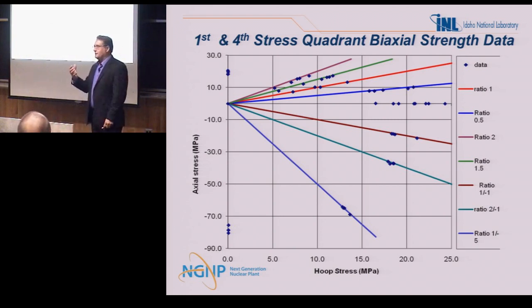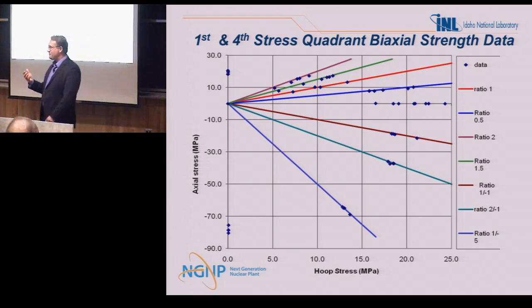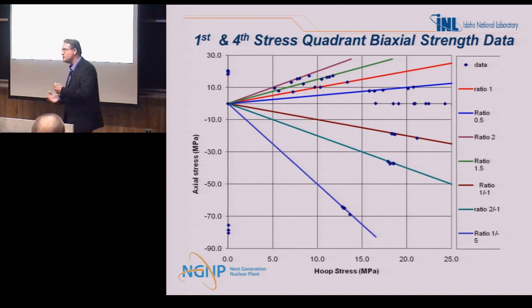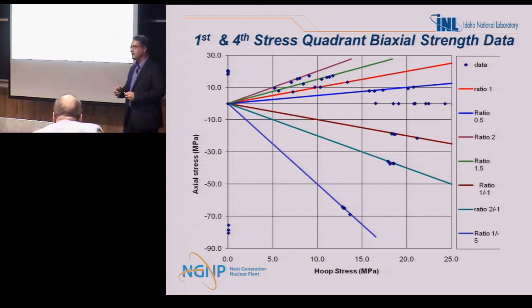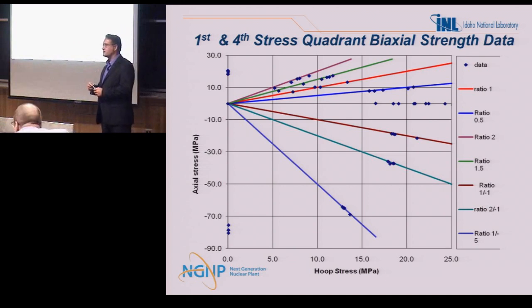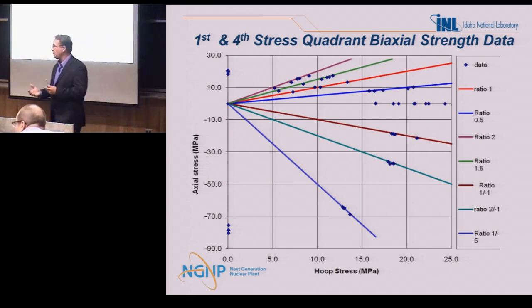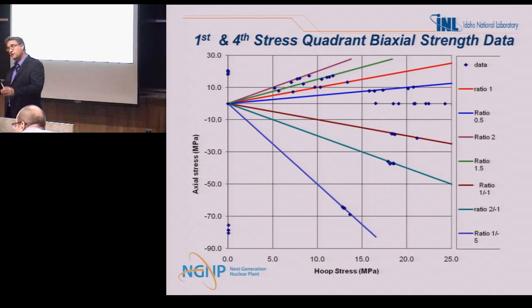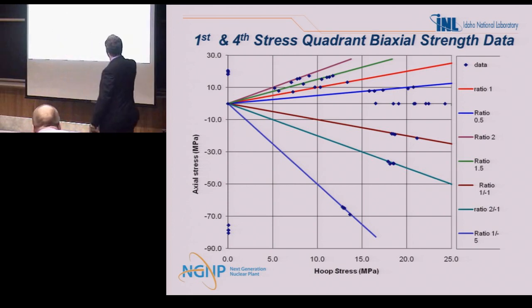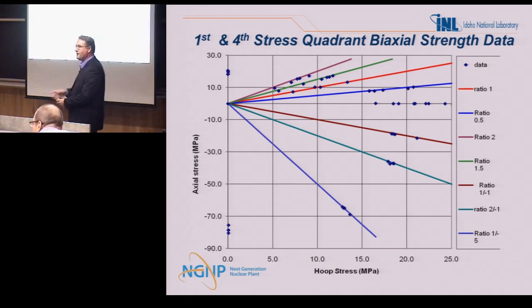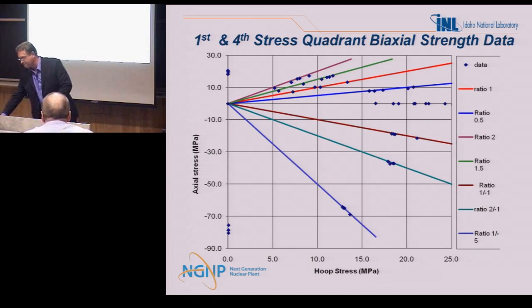We had these, in the graphite we were actually using, it was a fairly new graphite, and they hadn't quite gotten to production, and as a consequence we actually found somebody's shoelace in the graphite. Didn't work out real well for fracture toughness, but they got it, they figured it out, and it works out pretty well. This is a later batch, okay?